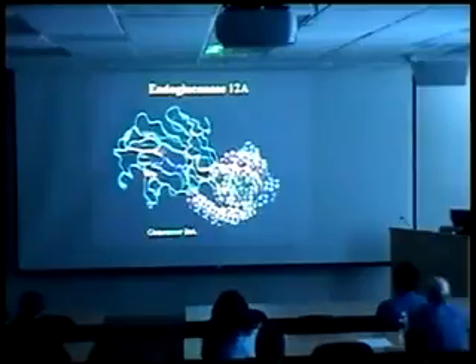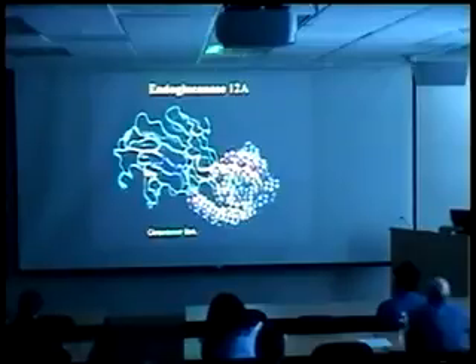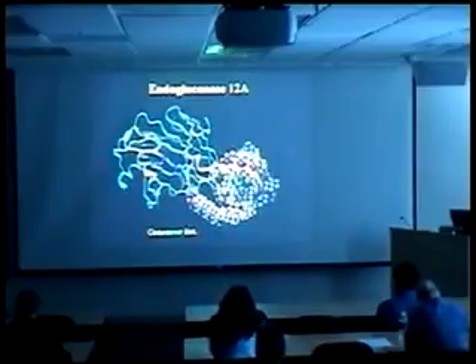And these are the catalytic site residues that are involved. This is just a model to show you roughly what size we would expect for these stimuli-responsive polymers relative to this particular enzyme. What we do is go in and genetically engineer handles here by putting in cysteine residues at defined positions and then hooking the polymer up. And by deciding where you put this hook, you can move the polymer closer to the enzyme active site or farther away.